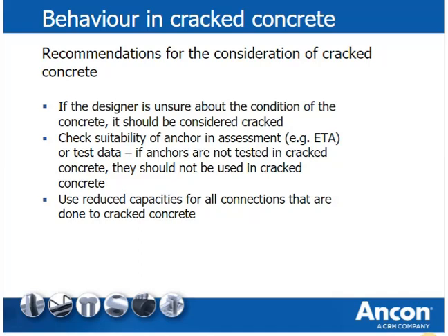If the designer cannot be certain that the concrete where the anchor will be placed is under compressive load in all directions over the entire lifespan, an anchor suitable for use in cracked concrete should be used. Connections to the bottom of a concrete slab should always be considered as cracked concrete. The assessment of the fastener should specifically mention that the anchor is suitable for cracked concrete; otherwise the fastener should not be used in that application. Even anchors suitable for cracked concrete will have reduced capacities, and the designer must apply the correct factors in the calculation.